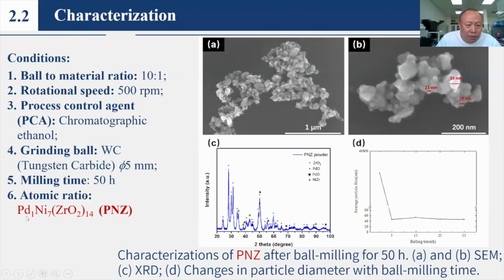This is the PNZ samples. A and B are SEM pictures, and C is the XRD pattern. We can find there is zirconia, palladium oxide, palladium-zirconium alloy, and nickel-zirconium alloys. And the grain size also decreases with time. Because zirconia is harder, the decrease is more rapid than in the PN samples.